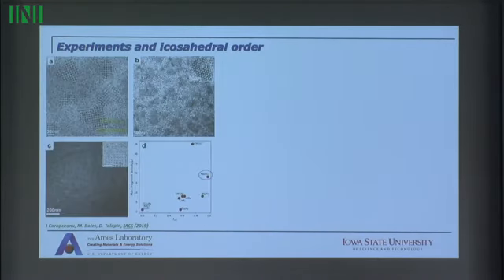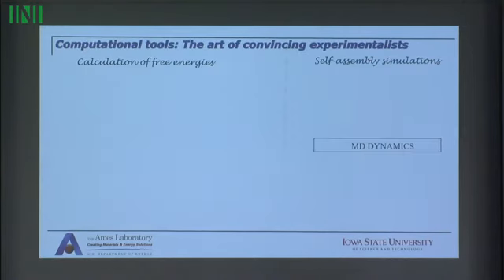I would like to mention these experiments that have recently appeared, where they basically show, among many other things, the fraction of icosahedral, and this is the type of fragments they have. So we see that they all have the icosahedral, they already form fragments, showing that there is this strong tendency towards forming icosahedra, and there are many more. Actually, in the 5 minutes I have, I do have 5 minutes, yeah?